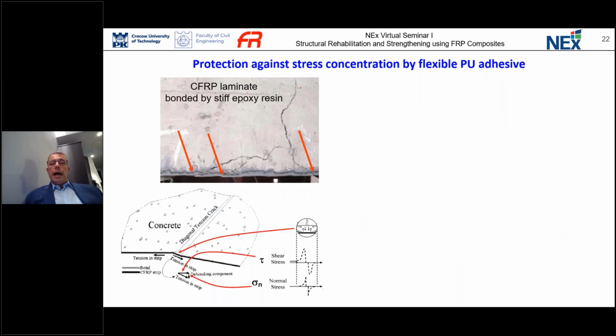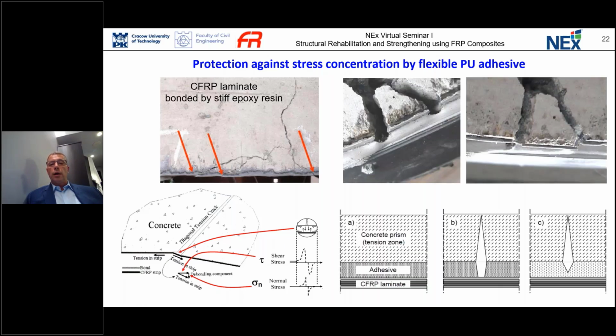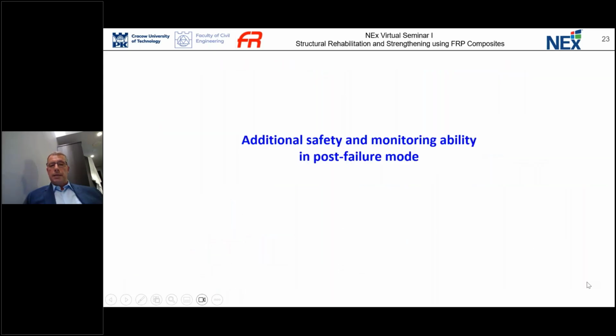So if we would like to protect the composite material, because of cracks in stiff epoxy resin, the crack generates in this place very high stress concentration that is acting on the composite material. If we have flexible material, you clearly see here that the crack is stopped in the flexible adhesive layer, and in this case we do not have the stress concentration attacking the composite material, because the stress is redistributed more evenly on the whole surface.